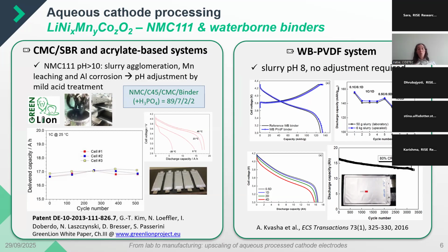In the NMC 111, when you have 1/3 of each of the transition metals - nickel, manganese, and cobalt - the pH, if the active material particle is not particularly surface treated, can be higher than 10, but not as high as with the higher nickel content oxides.